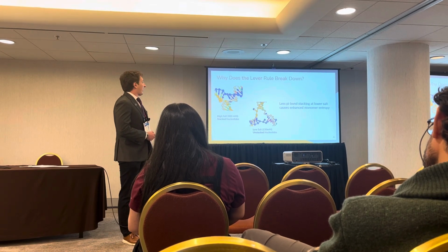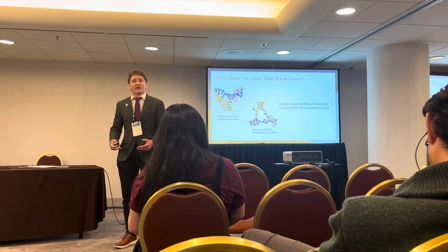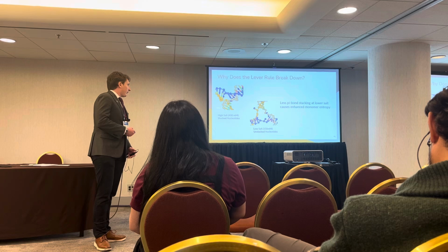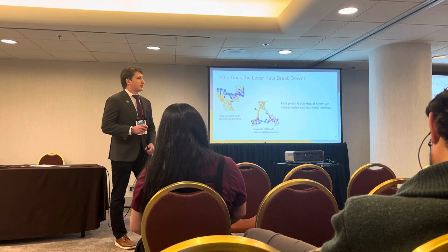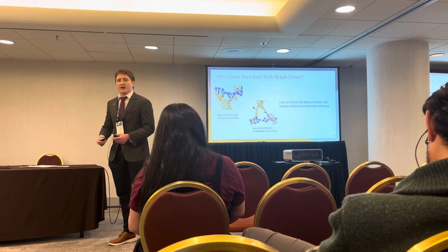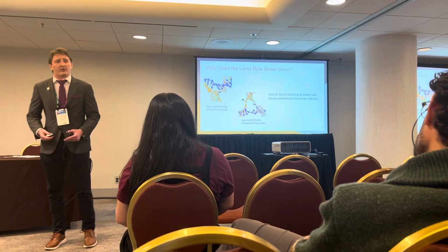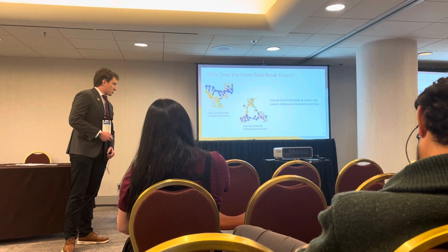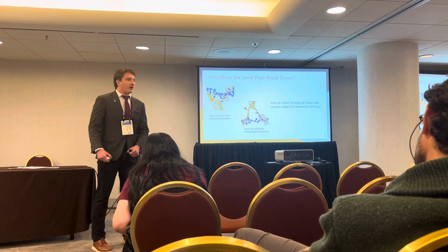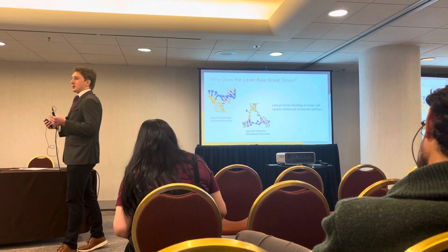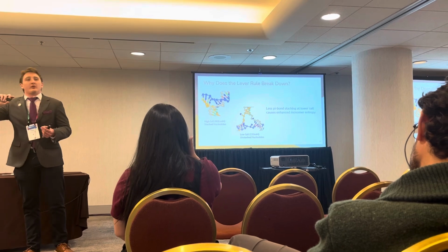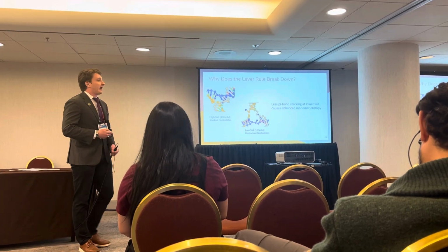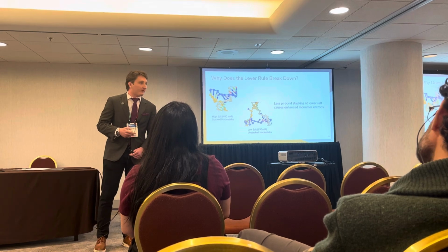And we see that under high salt, which to put some numbers on this, corresponds to a Debye length of about 6 angstroms, versus 9 in the low salt. When we're at high salt, the phosphates on that single strand are adequately screened by the solution, and as such, the pi bonds of the nucleotides are able to overlap. This confines some of the entropy to the overall structure. And yet in the low salt environment, as these nucleotides are able to sense each other and are not being fully screened, these nucleotides swing out of the junction, the pi bond stacking is no longer happening, and we have increased entropy to our monomers.